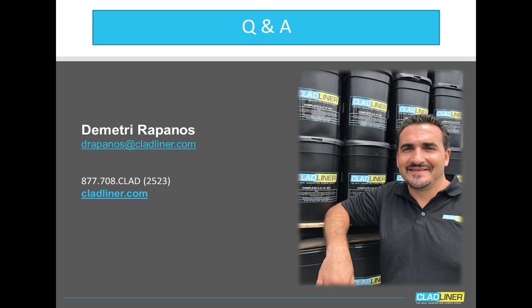Is there any type of testing that is done to ensure the minimum thickness of liner is applied and it has full coverage, like the spark test? Yes, so spark tests are not going to be easily done with this product because they have moisture in them. Spark tests work with 100% solids epoxies because there's no moisture in the epoxy, and it's looking for the moisture in the concrete behind it.